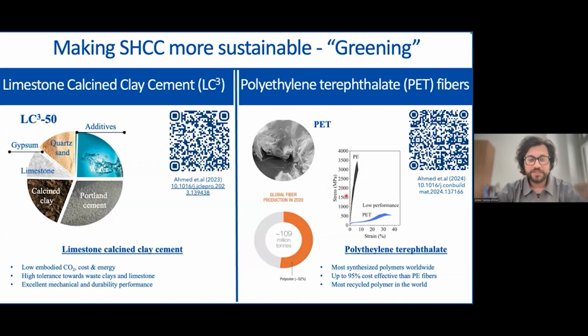But the issue is that if we look at the tensile response of these single fibers compared to what we typically use, which is PE, PET fibers have very low tensile strength as well as very low modulus, and they are highly compliant. You can see they deform at very low load levels. They start this plastic deformation, which is quite extensive deformation here. But that doesn't automatically mean they cannot work in SHCC. Again, in another study linked here by QR, we have shown that we can actually design PET reinforced SHCC using the micromechanics-based criteria which is needed for strain-hardening cementitious composites.